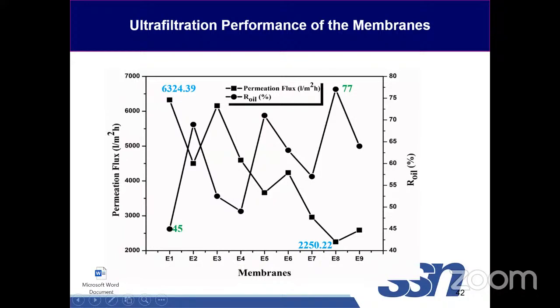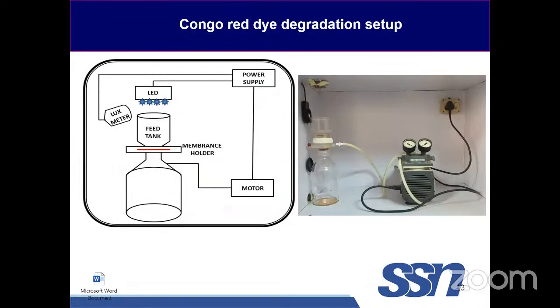This is the setup that we utilize to check the dye degradation efficiency, where we have taken Congo Red as the dye solution for our work. This is a feed tank in which we have taken the dye solution. This is the visible light meter which is used to measure the lux value that is coming out from this LED. And this is the photocatalytic membrane where we placed it, and the dye solution passes through this membrane.